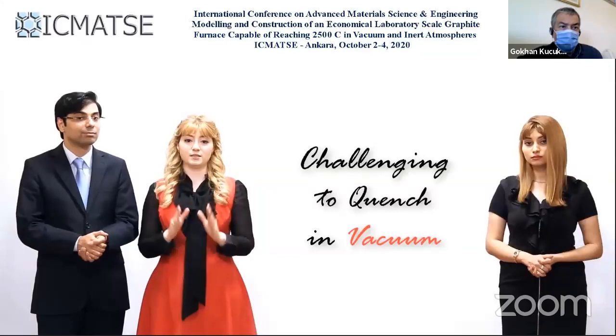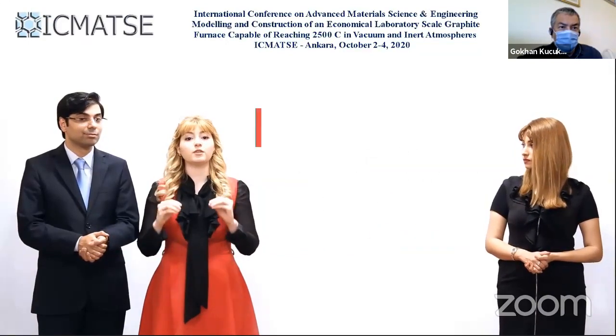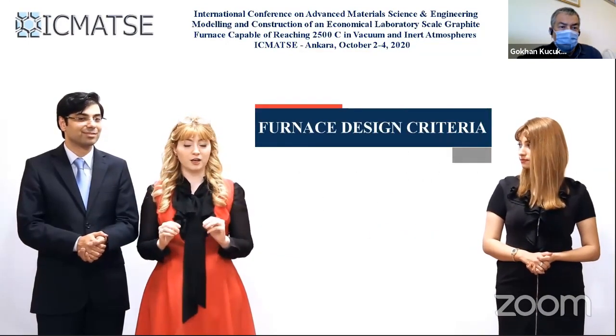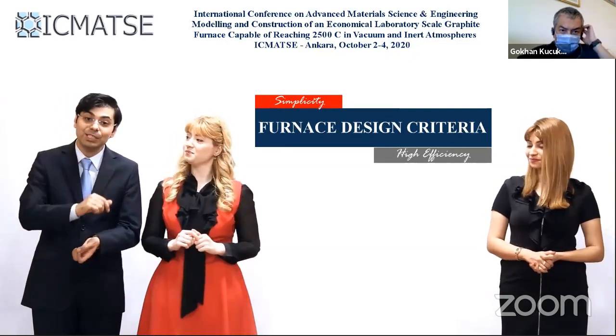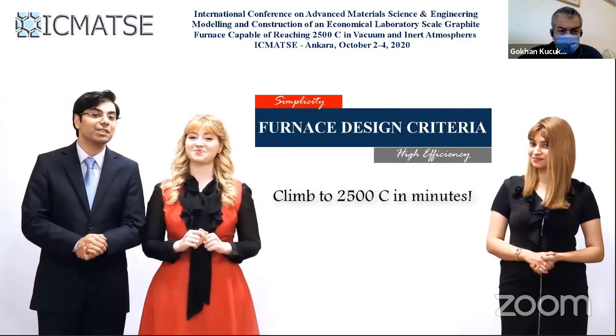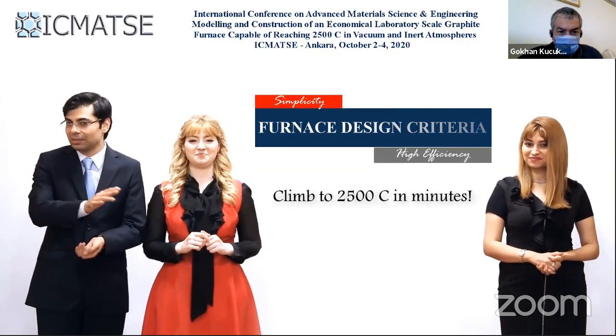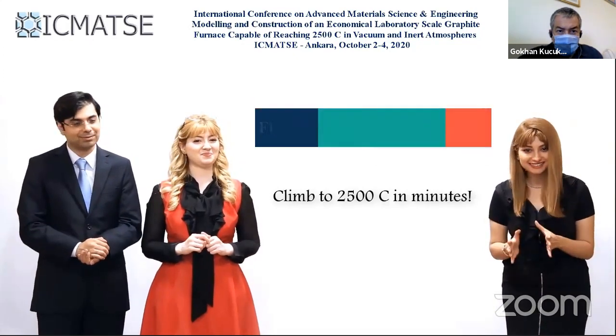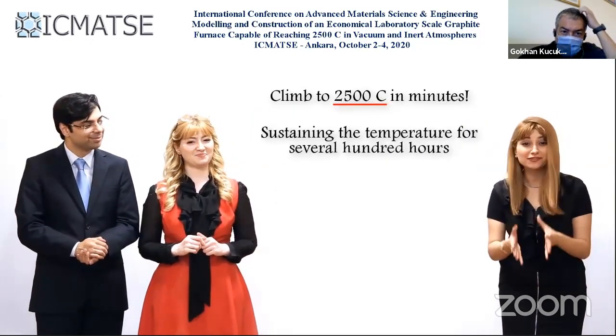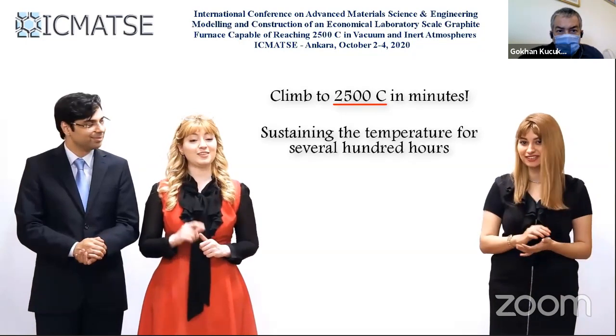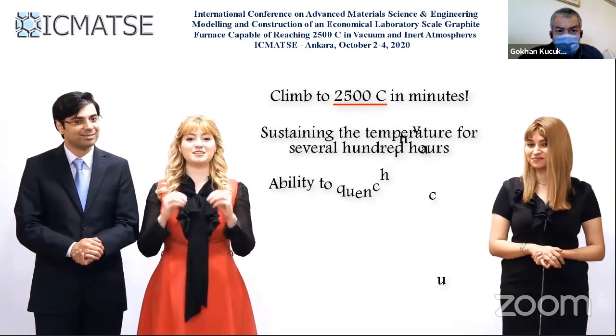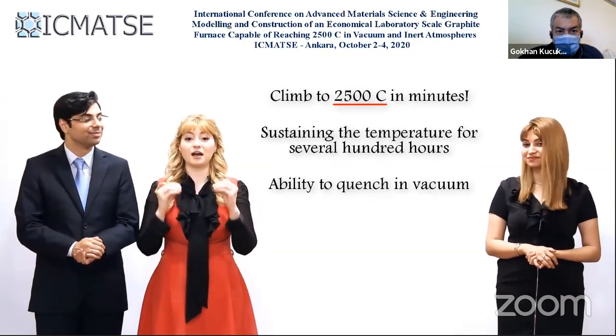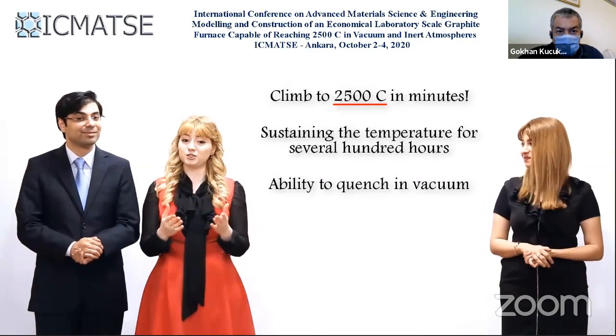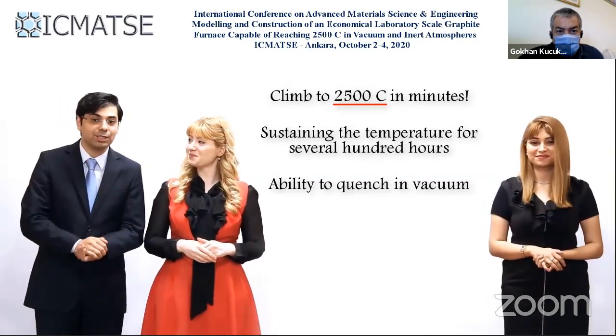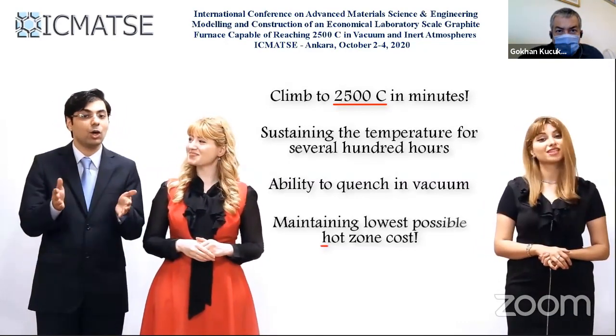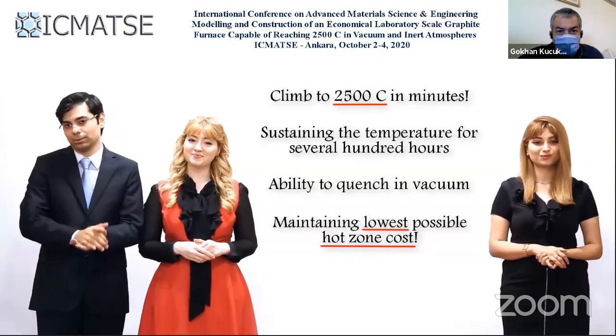So with these points in mind, we proceeded with the following design criteria for the furnace. The ability to reach 2,500 degrees Celsius in just minutes. Capacity to sustain the mentioned temperature for several hundred hours if necessary. The ability to cool down the furnace at very high rates without using any fluids for quenching purposes. And most importantly, maintaining the cost of the main hot zone as low as possible.